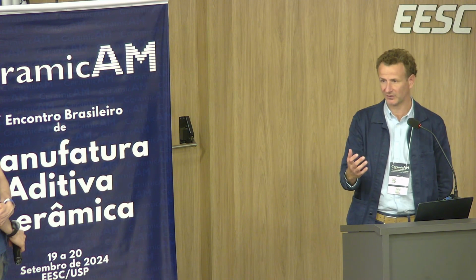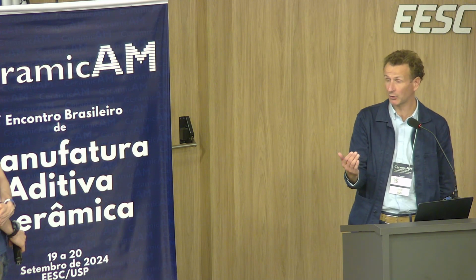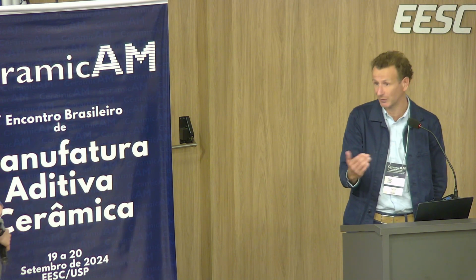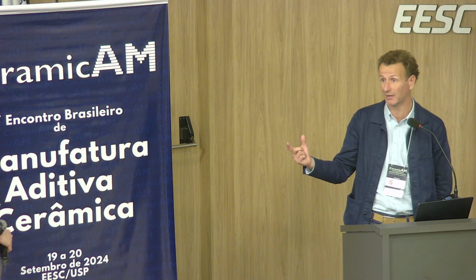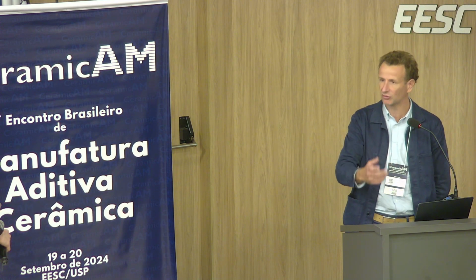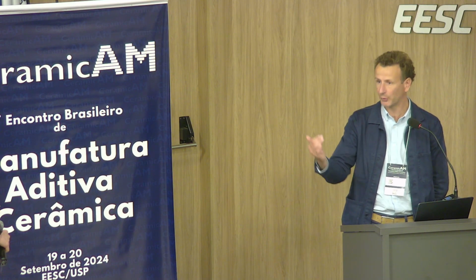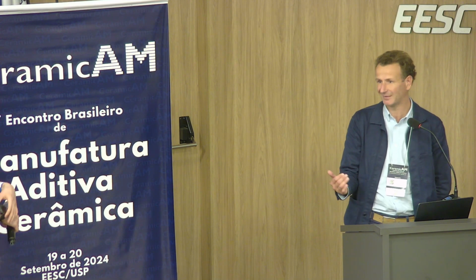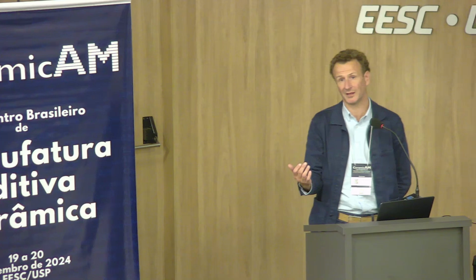In the ceramic world, they already know this kind of limit, because that's the case also with injection molding. You have a high quantity of binder, so you have long debinding times. So yes, we are trying to develop collaboration with universities and institutes to reduce debinding time, but it's difficult and it takes time. Also, 3 to 4 days is a short one. If you want to debind even very thick parts, you need a longer debinding stage. We are developing things with microwave debinding, for example, to try to shorten it. It will come, but it needs a little more time.